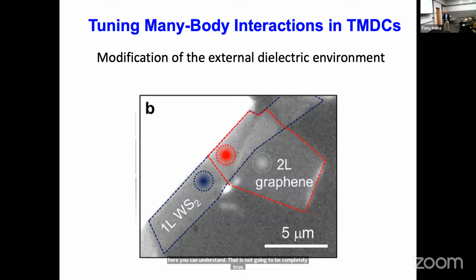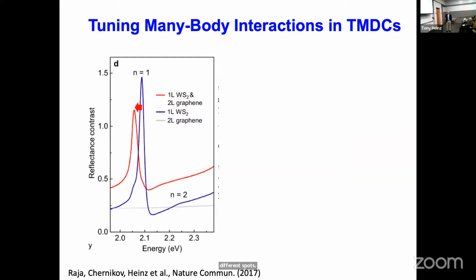Let me show you just experimentally a very straightforward kind of experiment. We have a monolayer of one of these semiconductors, and then we put a little bit of graphene on top of it. And the scale is big enough that we can shine our laser in different spots and do the spectroscopy and just compare what happens. So this is an illustration of the lowest lying state, this 1s state. And here's the feature you get with the material without any graphene on top of it. You put the graphene on top of it, it shifts down to lower energy because you get a lower energy scale from the reduced Coulomb interactions. Not such a big shift because a lot of the screening is inside the material, but it's very clearly present.